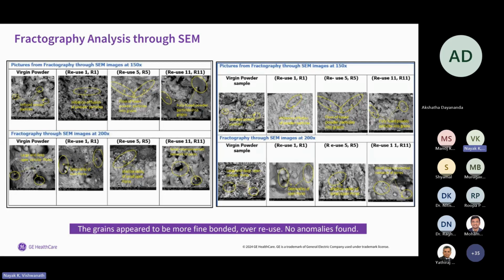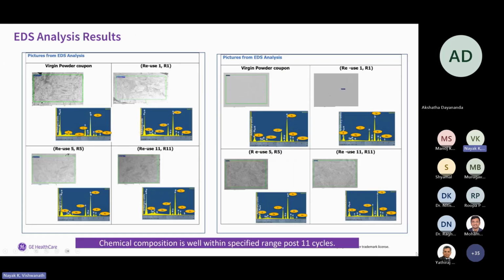But we did up to 13 reuse cycles. We stopped at that, but we kept the line at 11 reuse cycles. This is the typical standard that we used to keep in this case. We also do the EDS analysis, and the chemical composition, how it varies over a period of time for different reuse cycles. So we tried first reuse, virgin, and 5 and 11. So 4 different things, and we couldn't see much of a difference, and it was well within the range.